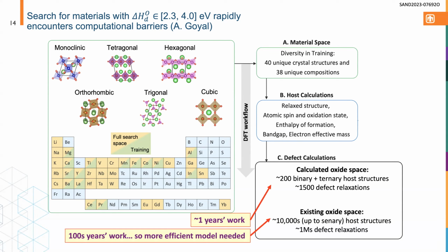When this project started, it took him about a year's worth of work to compute about 1,500 defects in around 200 binary and ternary host structures. But if you look at the Materials Project in terms of available oxide space in this orange color coding, there are up to tens of thousands of materials, up to senary compounds, millions of defects that you would have to relax. So completely intractable.